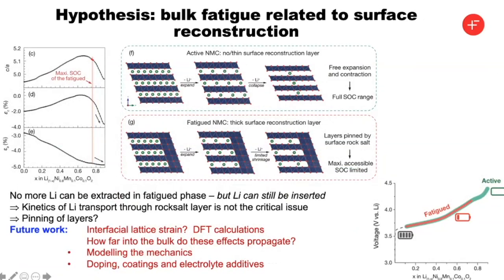So we're going to at least hypothesize that the origin, at least, of some of this fatigue is related to the surface reconstruction. So we know that on discharge, we can get the lithiums back in again. So it's not per se the issue of the lithium not being able to move through the rock salt layer.